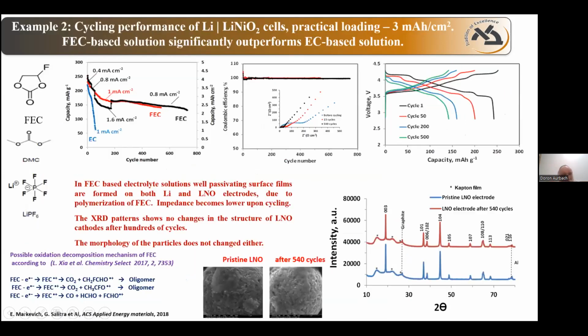Now going to the more challenging situation with LNO, we start with very high specific capacity, 250, and this is only by charging up to 4.3 volts, no more. We have some capacity fading, but we can stabilize the material during hundreds of cycles up to lithium metal when we have this type of electrolyte solution.